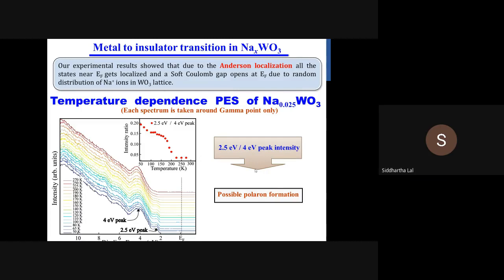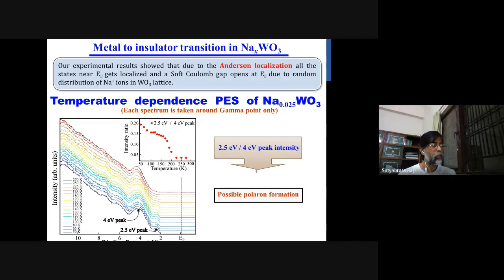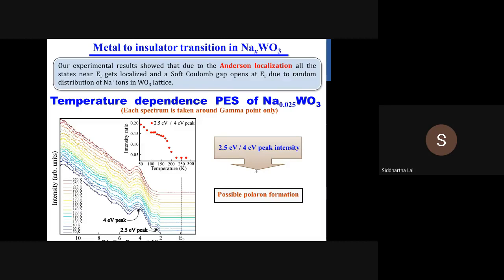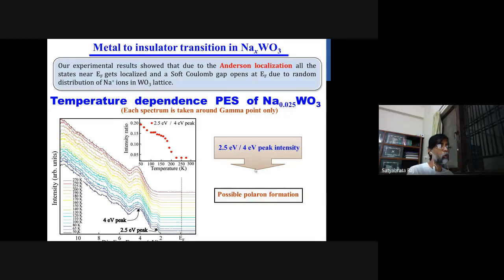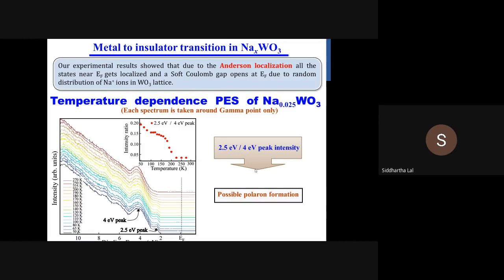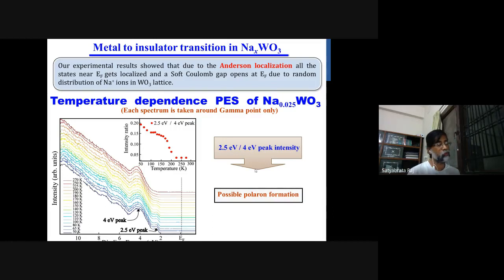The better way to see it would be at, let's say, 0.58 doping or 0.7 doping, coming down to low temperature. You would have to look at low temperature magnetoresistance, and there is a chance that as you crank up the magnetic field, the magnetoresistance will fall. That we have not tested. Magnetoresistance we have not done, only resistivity, which is not showing anything; in the metallic regime it is just metallic. Magnetoresistance is one of the smoking gun signatures for weak localization. That we can explore. Good point, well taken. So should I move on?